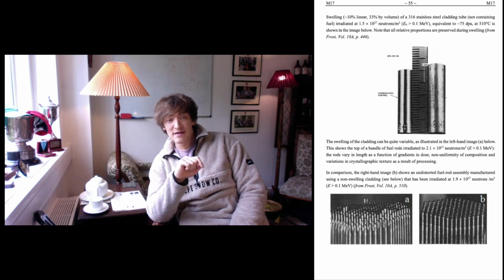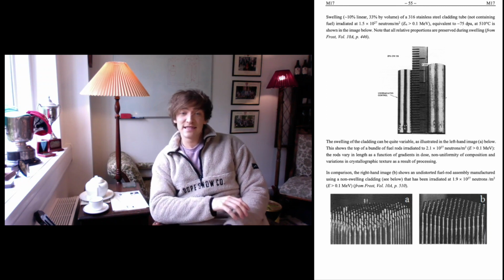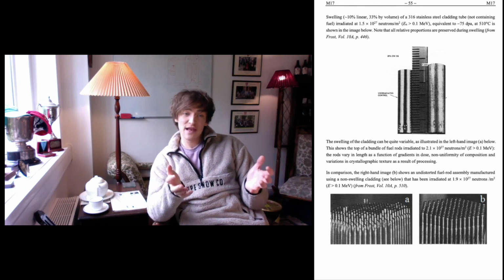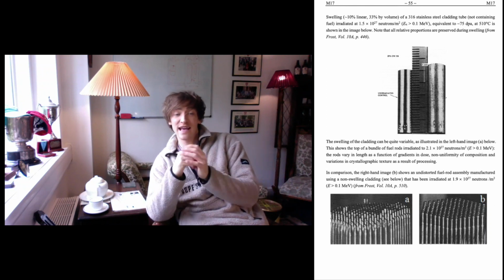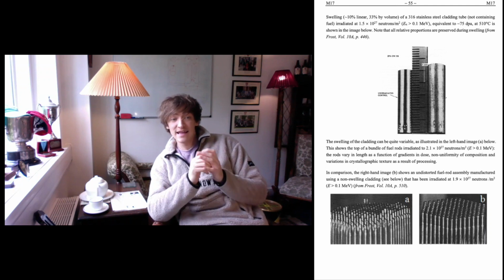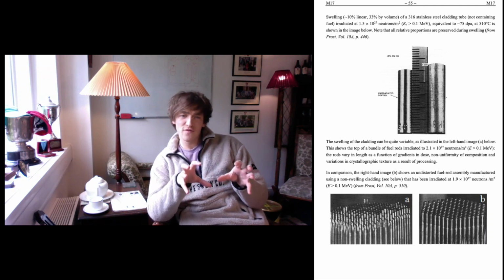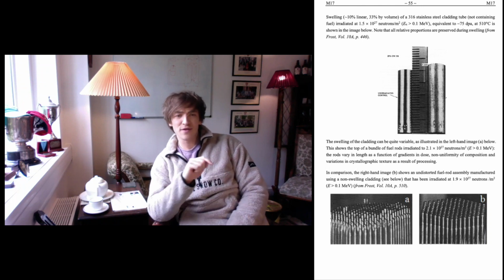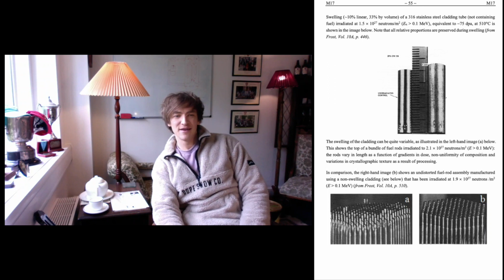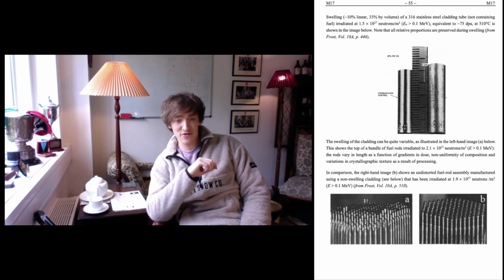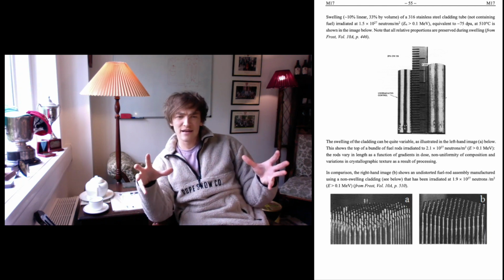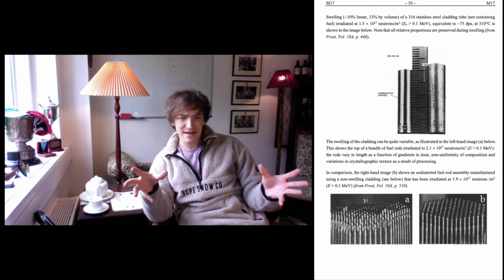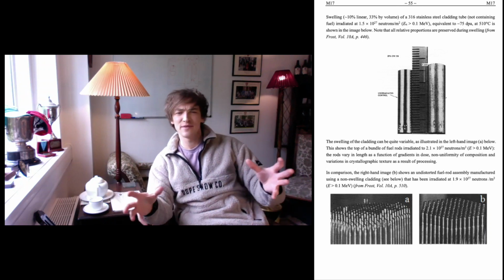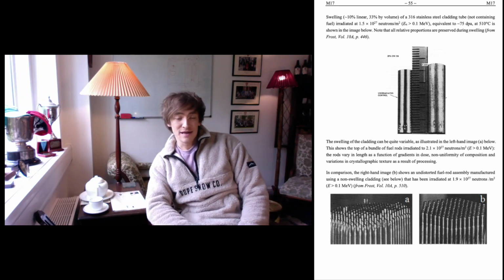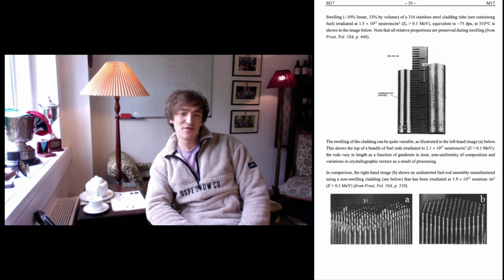Whereas if you look at image B, on the other hand, that shows an irradiated yet undistorted assembly because they've used swelling resistant cladding irradiated to effectively the same dose. And that indicates the significance of ensuring you've got uniformity in the production of your rods. You do not want the fuel assembly shown in figure A. You want it shown in figure B because you can imagine it would be a nightmare to control a reactor where the fuel is not where you think it is. You're going to get hot spots and it becomes a bit of a nightmare for almost everyone involved. Reactor physicists will not be happy if you give them dodgy cladding where all the fuel rods change in shape relative to one another.